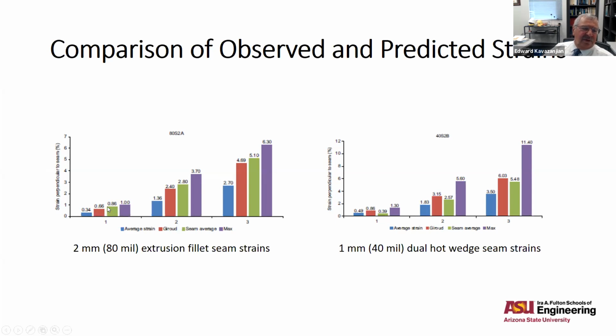So relatively good agreement between Giroud and what we measured, but the maximum, which we attribute to imperfections and non-uniformities in the seam, was greater than the average and greater than what Giroud predicted. And that pattern holds all the way through. So here's a somewhat higher strain level. Again, what Giroud predicted, the average we measured in the seam, and the maximum. And then we see the same pattern here at the larger strain, where Giroud and the DIC results are converging and the maximum is greater.